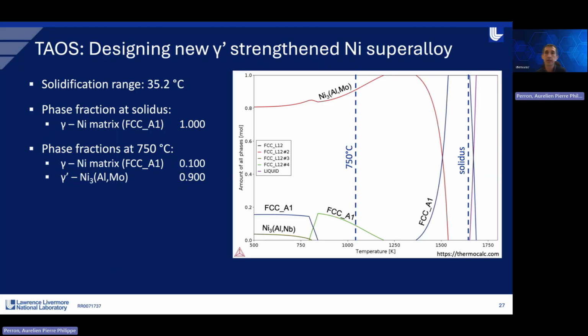So this is the result of this optimization. It takes, I think, between minutes and hours. I don't remember exactly, but that's fairly quick. On the right side, I'm sorry, that's what we call a property diagram. That's the evolution of the phases as a function of temperature. It has been plotted using the alloy composition that has been designed by TAOS. You can see that the solidification range, this small delta here, is below our 100 degrees C, at 35 degrees C.